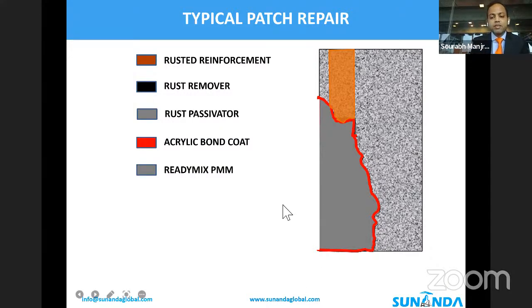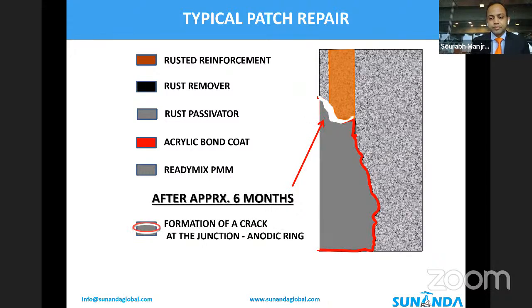Despite that, the problem that they were facing was that after doing this, within 6 months, they were facing the issue of anodic ring corrosion. That is, at the junction or at the interface of the patch repair and the embedded steel, cracks were developing. And once again, the structure was vulnerable to contaminants, to chlorides, and in turn, a failure of the entire repair. That's when they approached us to solve this problem for them. We studied the case, understood the report, NDT report, and then recommended the remedial action, which I'll come to.